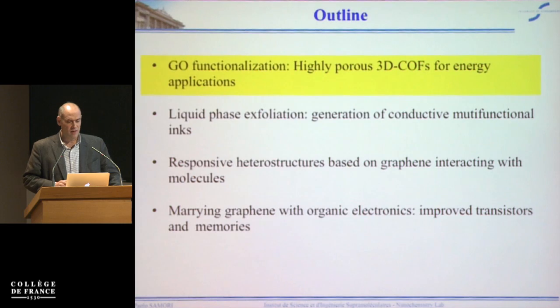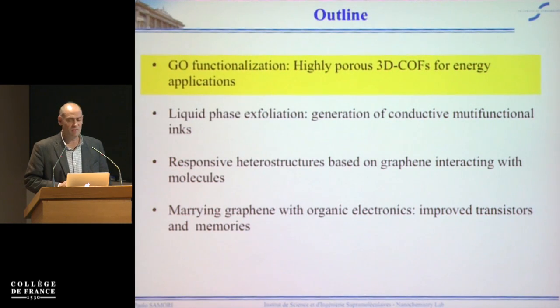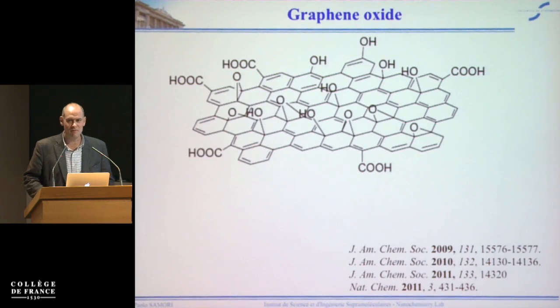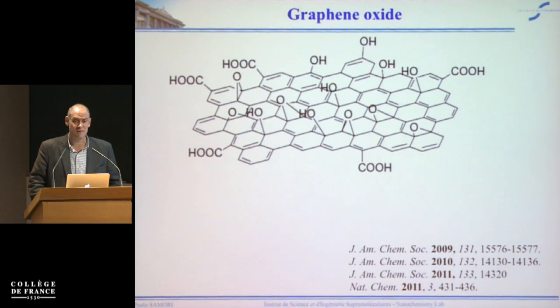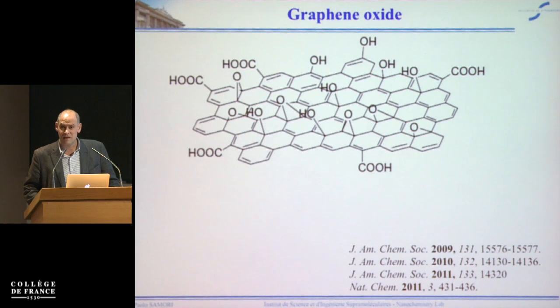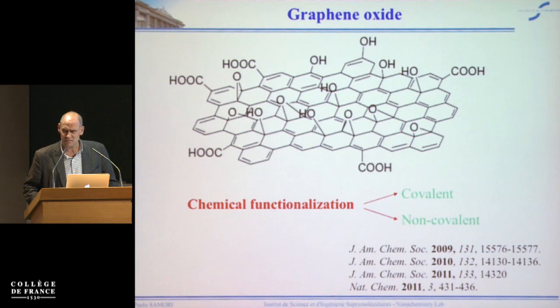So I will start with playing with graphene oxide. Graphene oxide actually is the easiest way as a chemist to play with graphene because it can be easily produced. You start from graphite powder, you do some oxidation cycle like Hummers' method, and you create this graphene oxide. They are fantastic in the sense that you solve all problems related to solubility. You have a lot of different functional groups that you can use to do functionalization at the covalent and non-covalent level. Of course, the physicists do not agree with this because most of the exceptional properties of graphene are lost. But nevertheless, you can do a lot of different chemistry.